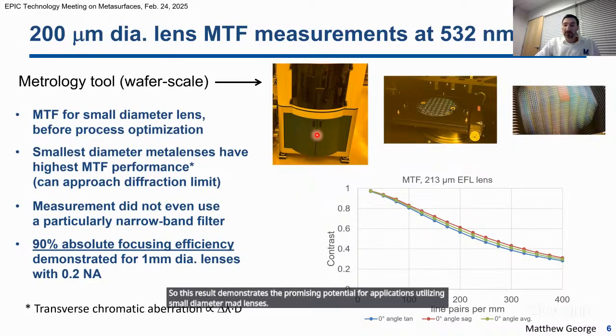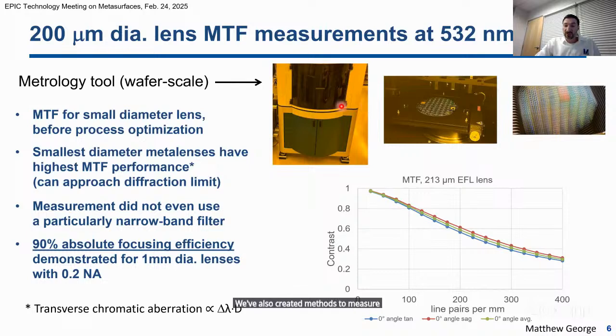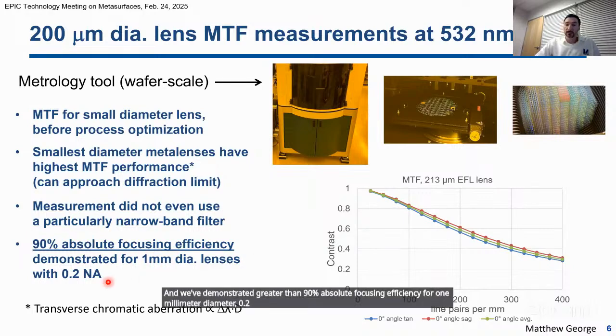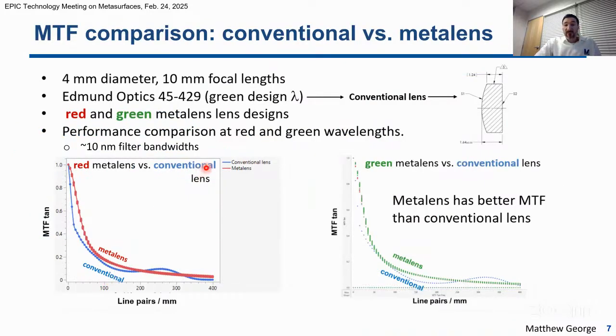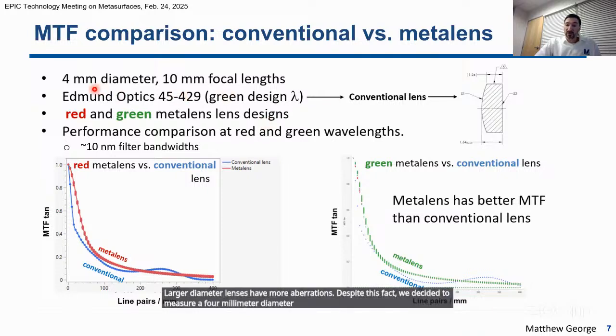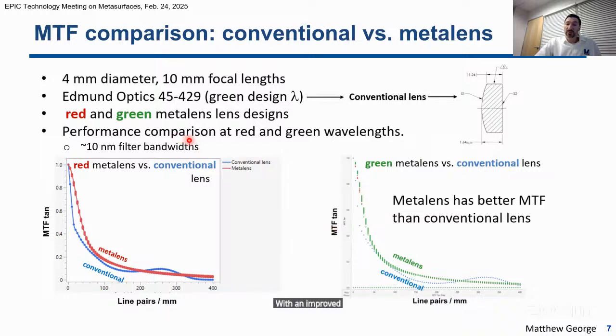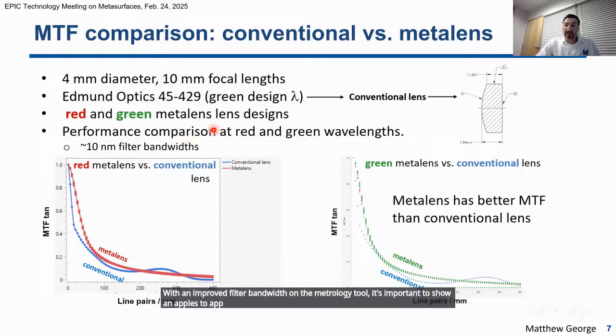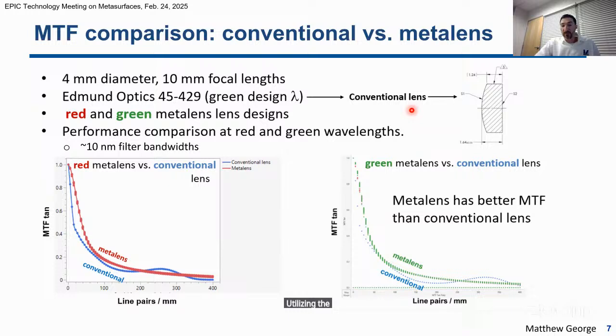We've also created methods to measure absolute focusing efficiency using this tool, and we've demonstrated greater than 90% absolute focusing efficiency for 1 millimeter diameter 0.2 NA lenses. Larger diameter lenses have more aberrations. Despite this fact, we decided to measure a 4 millimeter diameter conventional plano convex singlet lens from Edmund Optics and compare that to the performance of our red and green metalenses with the same diameter and focal length. And even though our metalenses would show better performance with an improved filter bandwidth on the metrology tool, it's important to show an apples-to-apples comparison to a traditional lens utilizing the bandwidth requirements of the end user's applications.